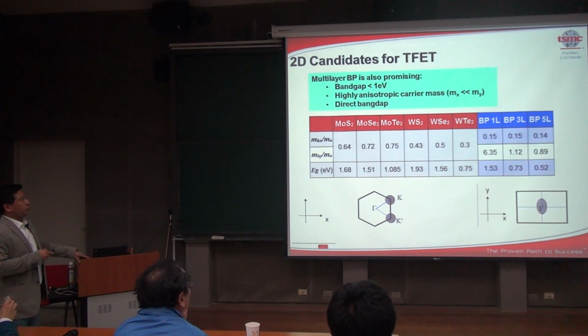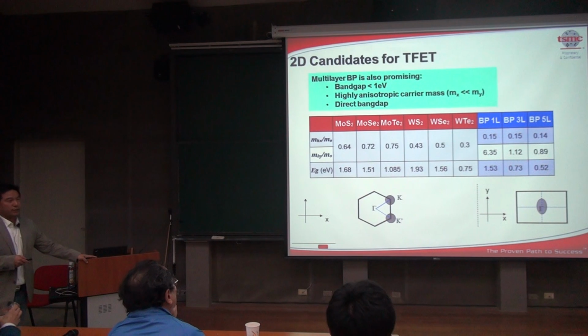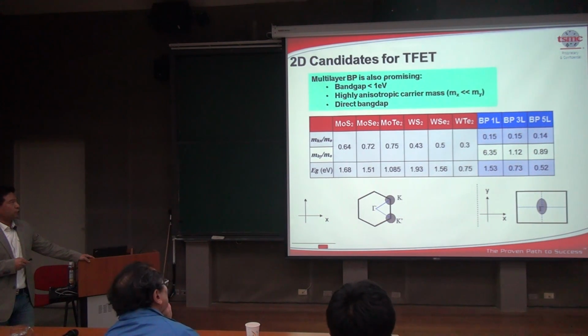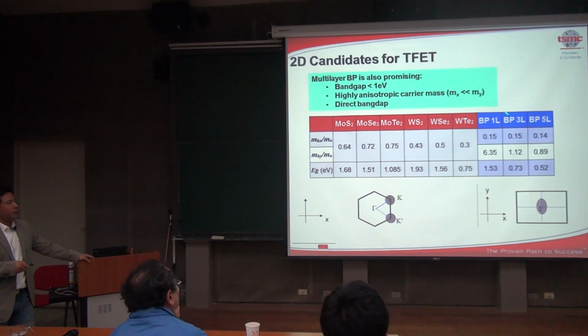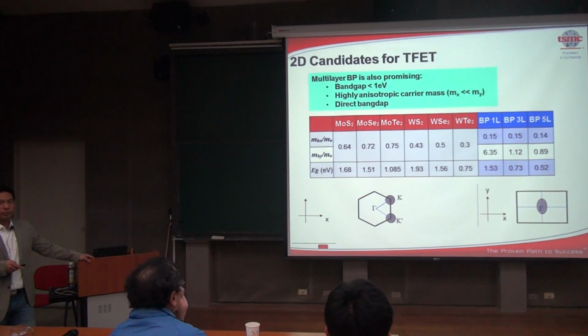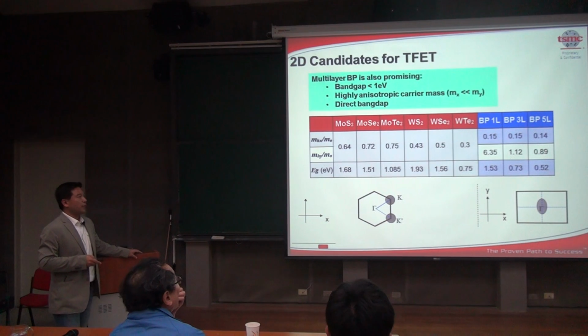So multilayer black phosphorus is actually quite promising because you can maintain a direct band gap for any number of layers. You can tune the band gap by the number of layers. While in the case of TMD materials, remember that they become indirect band gap when you have more than one layer. That means your tunneling current and probability will start to suffer significantly.